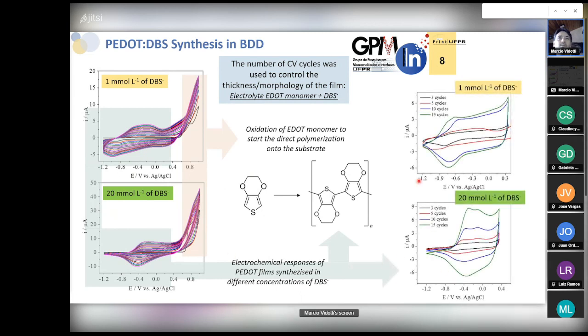And studying the modified electrodes, we have tried to grow this polymer for 3, 5, 10, and 15 cycles. So we are increasing the thickness of the electrocatalytic material. And here are the results for the materials synthesized below the CMC and above the CMC. It's very important to observe that the electrochemical responses are quite different, but we are talking about the very same electrocatalytic material. So it's quite interesting to study a little bit further why these changes are occurring.